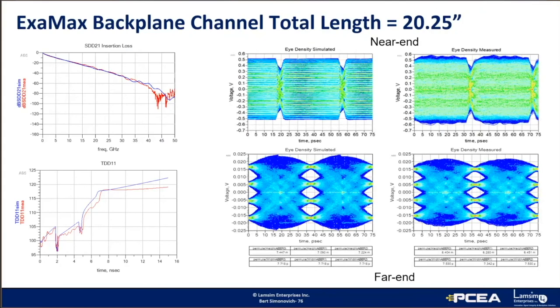And using the IBIS AMI modeling feature in the Keysight ADS tool, we can get some eye diagrams, shown here. The top ones are at the near end, or at the transmitter end. The ones at the left are the simulation, and the ones on the right are the actual measurements. And you can see the measurement at the source is a little bit noisier, and that's because of all the impairments: impedance matching and the vias are also included, which I didn't include in this simulation.